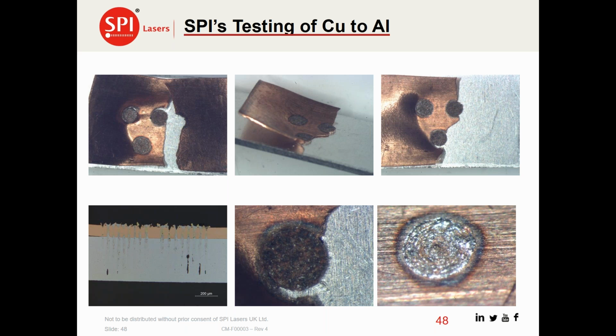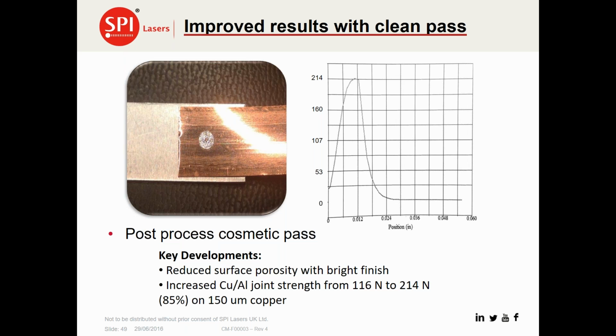This is an example of where we tried a post-process cosmetic pass. So once the weld had actually been done, again this is a spiral spot weld, once it had been completed, we tried a post-process cosmetic pass just to improve the look of the weld itself. What we actually found, though, is that in some cases, not all cases, this actually increased the strength of the weld also. In this case, for copper to aluminium, the joint strength increased from 116 newtons to 214 newtons. That's an 85% increase in weld strength just by doing a pass. We believe that's just due to a remelt of the material on the top copper surface layer.